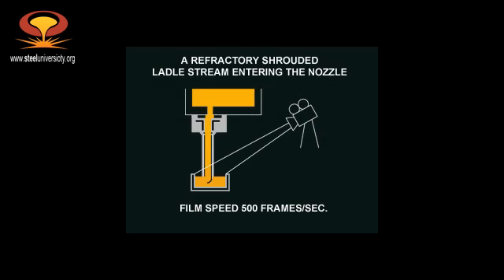In order to prevent that taking place, we use submerged entry nozzles. Here is an example of steel flowing from the ladle into the tundish through a submerged nozzle. In this case, the black patches of slag that we saw in the previous sequence are no longer present — the surface is bright and clear. For this reason, we need to add synthetic tundish flux to prevent re-oxidation of this steel.